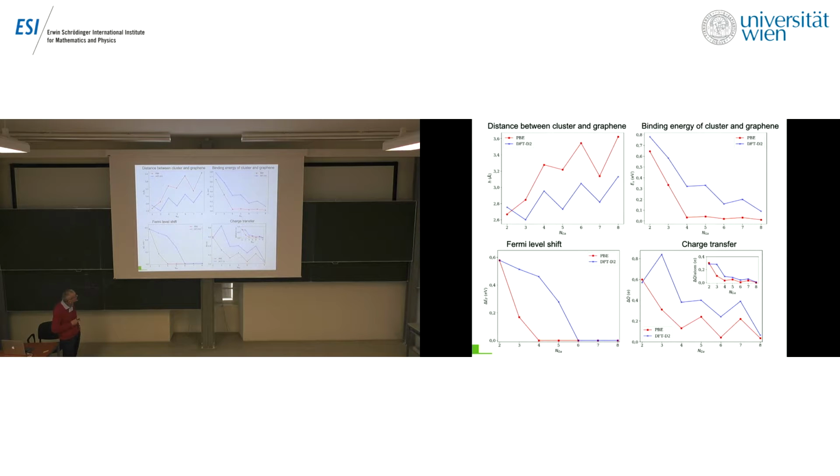And definitely for van der Waals forces the charge transfer is stronger, because those atoms are closer to the surface. You can see it here. Also, what is interesting, it's not some error in calculations, but for odd numbers of atoms, the distance between clusters and the surface is smaller. So also, charge transfer should be bigger, yeah, here. Maybe because if you have that odd atom, it doesn't have a free neighbor to react, and then it may react more with the surface.